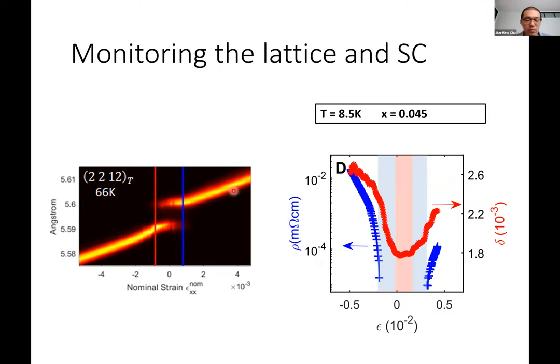So with these measurements, we can now go back and check whether this whole idea of detuning the crystal is truly suppressing the superconductivity. So we plot the orthorhombic distortion, which is the red curve, as a function of nominal strain, and you can see that there's a range where we are just detuning the crystal, so the orthorhombicity is unchanged. But then you can further distort the crystals, and you start to see increased orthorhombicity for both compressive and tensile strain. And only once you pass some critical strain value, you start to see that the resistance, which is the blue curve, goes from zero to non-zero.